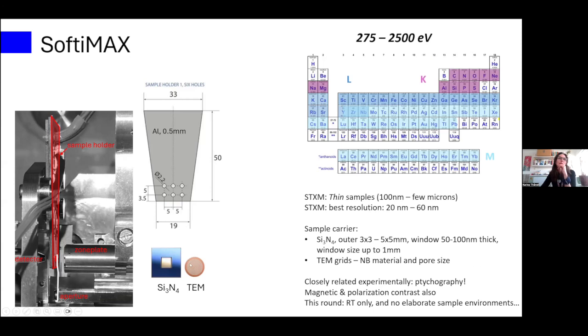And the pore size, right? So again, you want to have a fairly open spaced grid, but obviously it still has to catch whatever you try to do. And we've had this very unfortunate event once before. With the grid, we cannot look through the grid, right? We have to look through the pores. So the sample has to be in the pore, not on the grid. It's very important to keep in mind.